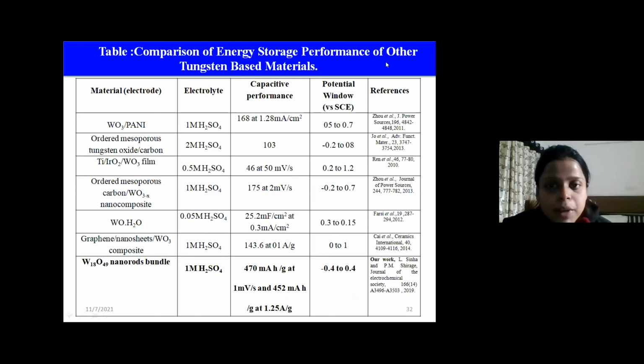So this is the comparison of the energy storage performance of other transition tungsten based materials. And here also we are seeing that we have used 1 molar H2SO4 for the energy storage measurement, and this is giving a higher specific capacitance in a large potential window of minus 0.4 to 0.4.